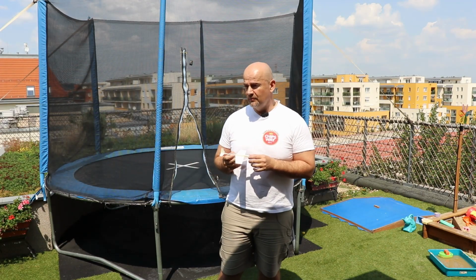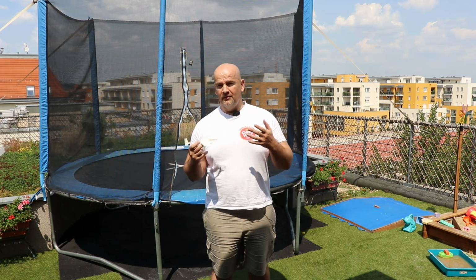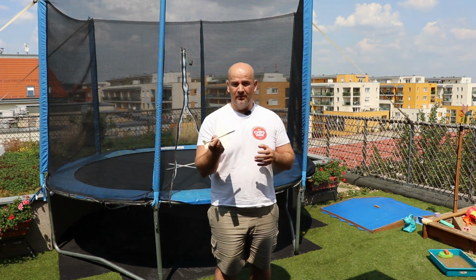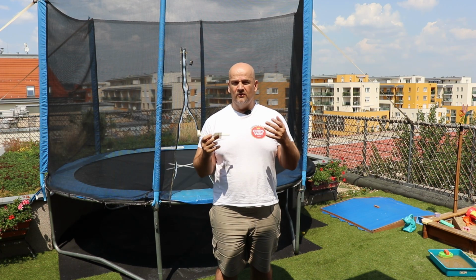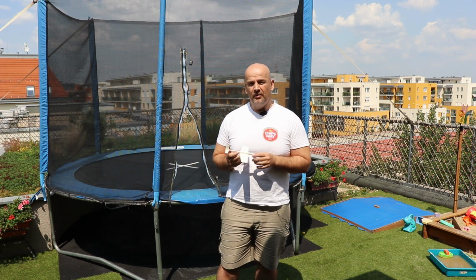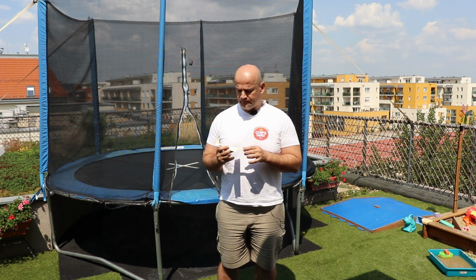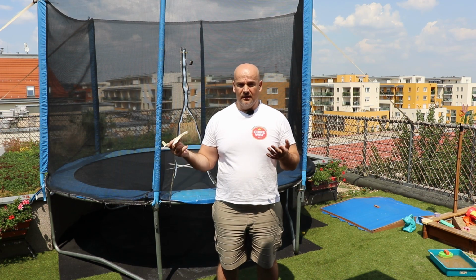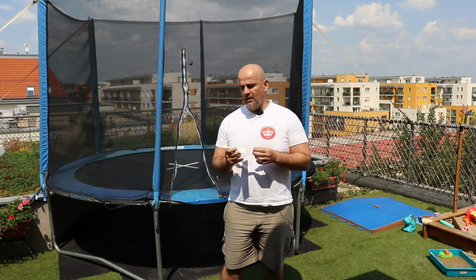And now the conclusions. Well, actually I'm really impressed with the 3D printed objects from lightweight PLA with their weight. Of course the strength is weaker compared to the regular PLA, but this is the price you have to pay if you want super lightweight objects. And you don't have to go to such high temperatures like I did. Printing at 240 degrees Celsius you can still have half of the density compared to the regular PLA. And the object is even nicer.